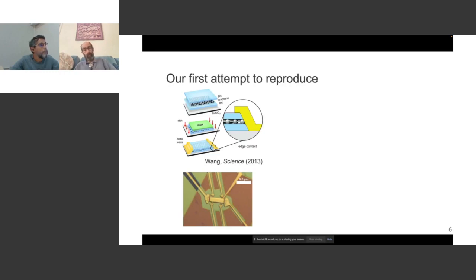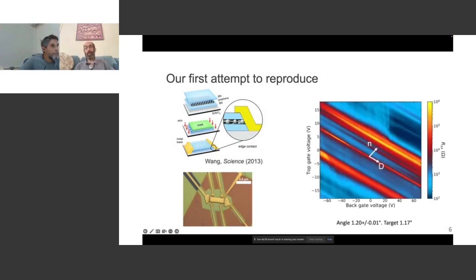And so this is a sample. You can see it's a few microns in size, and it has six contacts, so we can drive a current and measure voltages, and then there are gate electrodes that allow us to tune the density of carriers. And here's an example of how the conduction through the system looks. I'm plotting on a color scale the resistance measured on the voltage between two of these contacts when we drive a current, normalized to that current. So on a color scale, plotting the resistance as a function of two gate voltages.